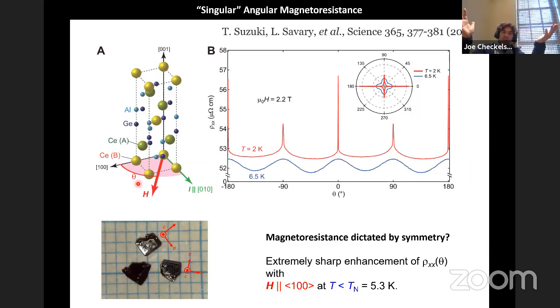So we were interested because when we examined these crystals, so here is a crystal, and this is showing the tetragonal plane. What we did was an experiment, which is very standard in the world of magnetotransport: we ran a current along one of the in-plane directions, and we rotated an in-plane magnetic field. And above the magnetic ordering temperature, it looked very conventional. I didn't tell you before about how these systems typically behave, but typically there's some symmetry-allowed series of cosines with which you can expand this response. And pretty much it looked like some series of cosines.